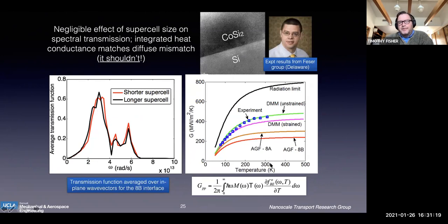We couldn't go above 300 Kelvin. David Cahill has complained to me that, Tim, you should have gone higher. The reason we didn't go higher is that these were measured also in Joe's lab with thermal reflectance, and the temperature coefficient of reflectivity for cobalt silicide happens to become insensitive to temperature above this point, so we couldn't go to higher temperatures.